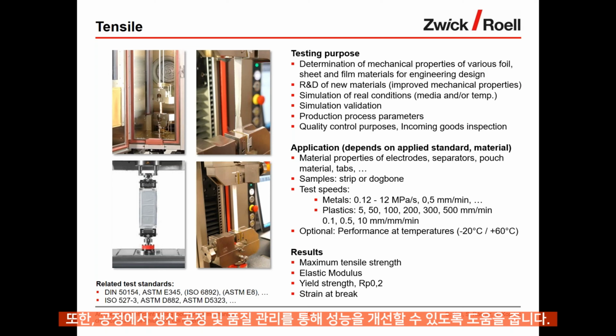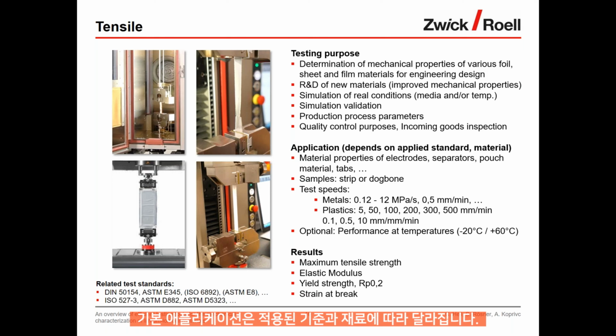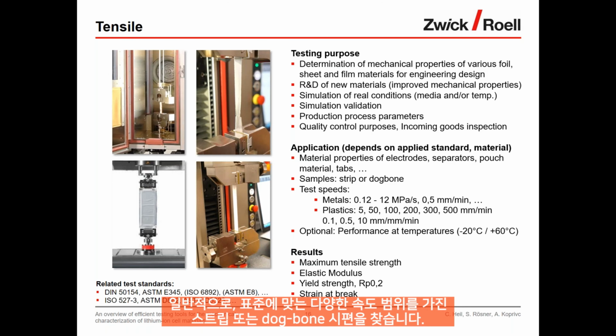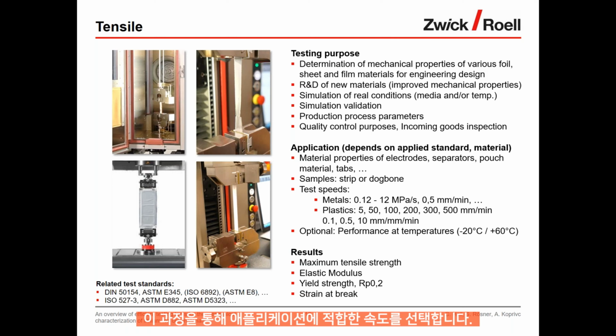A classical application, of course, depends on the standard and on the material, but typically we're looking at strip or dog bone samples with a various range of speeds that are given by the standards. So we need to make sure that you choose the right speed for your application. Especially if you compare your results with other laboratories or your supplier or your customer, make sure that you define all those test parameters very precisely so that you can actually compare the test results. Which results are we talking about? Typically maximum tensile strength, elastic modulus, yield strength, Rp0.2, and also strain at break.